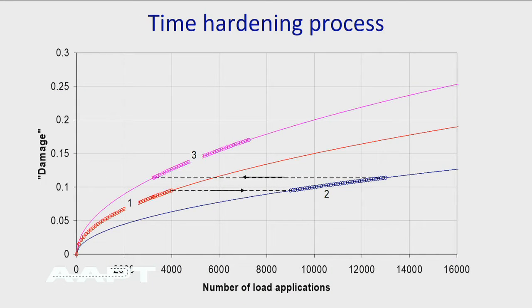How do we step between these? We use a time hardening process, which basically assumes that damage is irreversible. We've cross-checked this a little bit with a strain hardening process, which moves the other direction as we move between damage curves. Some change in the result. This was the assumption that we went with, which is no reversal.